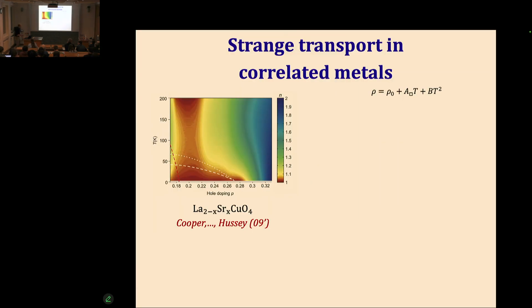And what is the magnetic field here? Yeah, so the magnetic field varies. If you're out here, you don't need a large magnetic field to suppress Tc. If you're here, you need a much higher magnetic field, just because Tc is higher. So the field varies between a few Tesla and a few tens of Tesla, like 30, 40 Tesla. For each point on this diagram it is different. What's actually measured is the resistivity as a function of both temperature and field for every point.